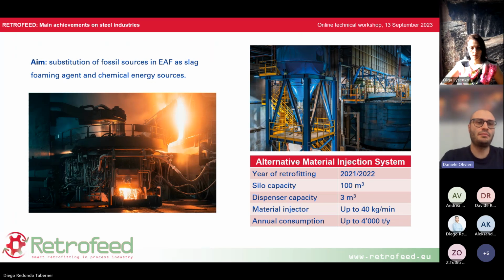So the aim is the substitution of fossil fuel with other materials, other feedstocks, in order to produce energy and to create a proper foaming slag in our electric arc furnace. As you can see in the picture on the left, this is our electric arc furnace with a lot of injectors and burners on the lateral side of the furnace. And so we tried several materials in order to produce chemical energy and to inject materials to replace anthracite and to make a foaming slag.